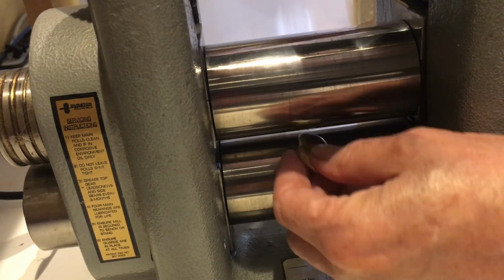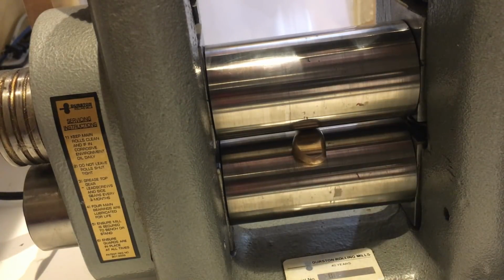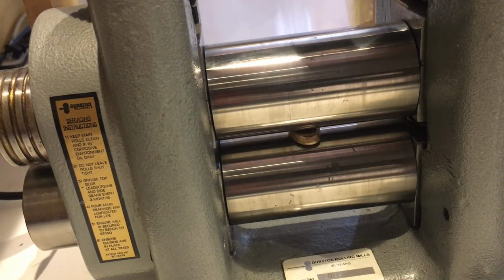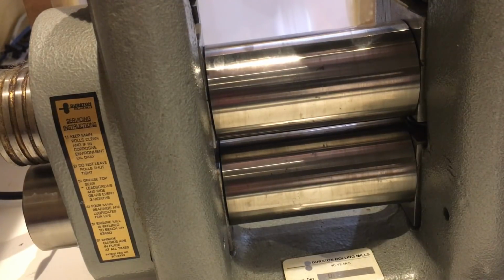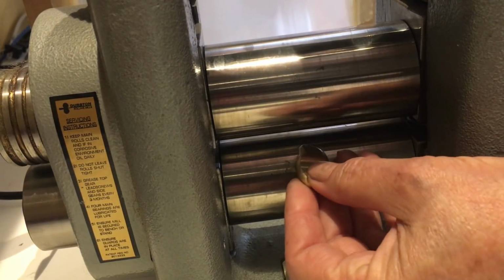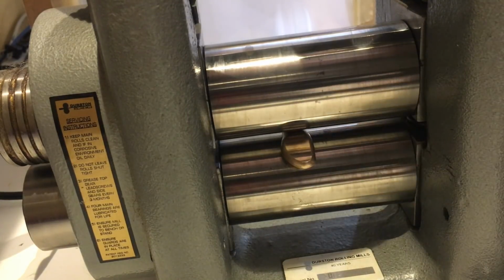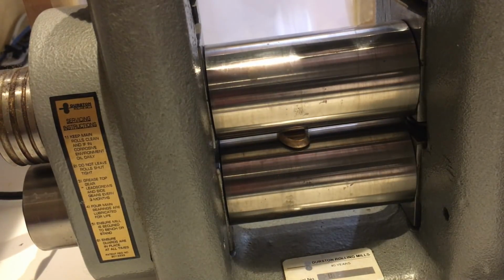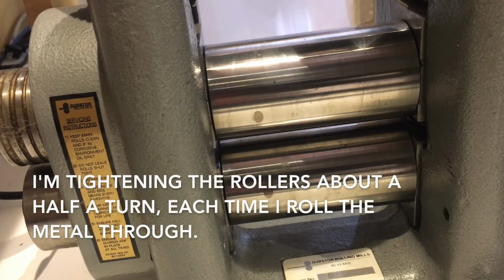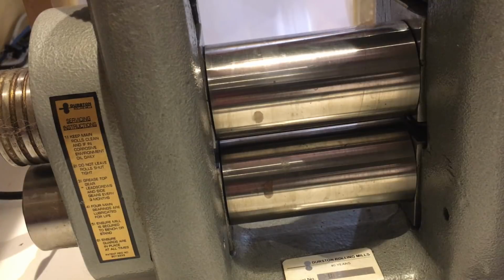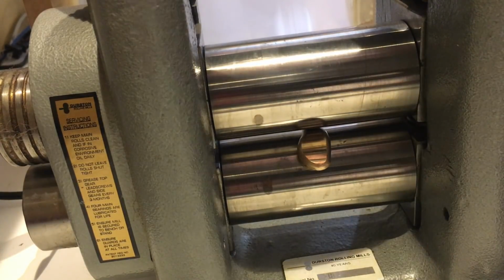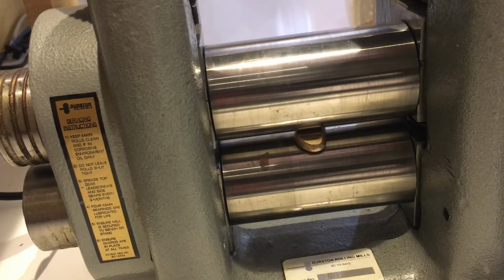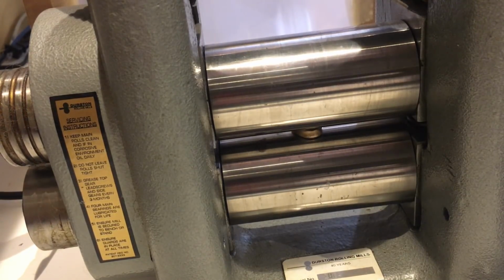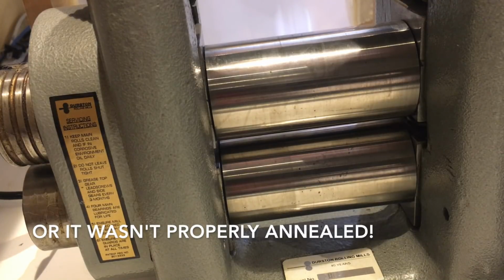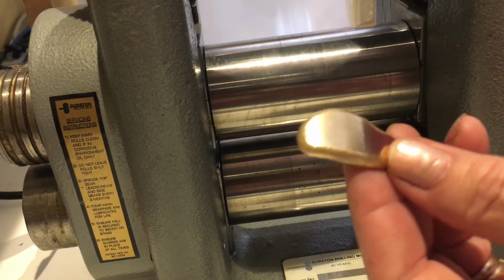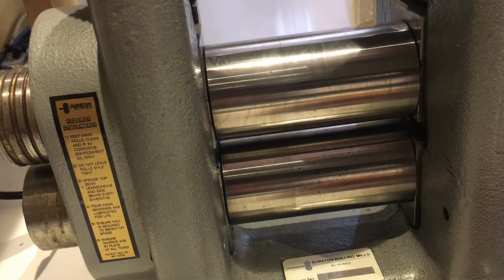So while I do this, I'm going to talk about some problems. If you get buckling, that can happen because you're changing your direction during rolling, like I talked about, from long to wide. So what you need to do is re-anneal and start rolling it through only in one direction. If you get cracks along the edge, the ingot could not be of uniform shape, or it was rolled too many times without annealing it. This is starting to get a little hard. I'm going to anneal it in a second after I finish babbling here.